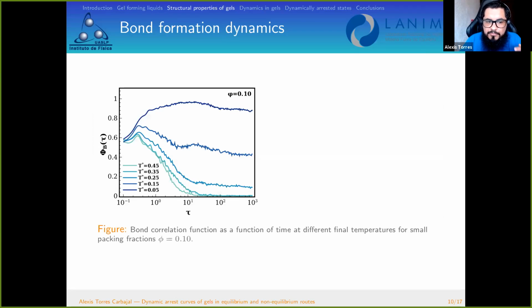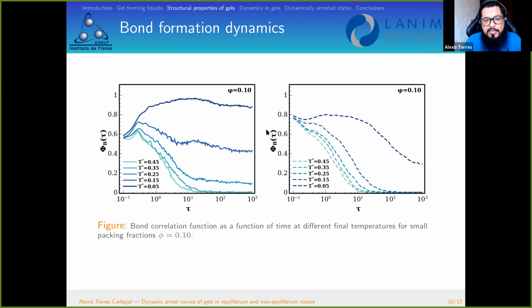So we determine this correlation, and we found that, for instance, at low packing fractions, the Lennard-Jones fluid at low temperature exhibits an increasing formation of bonds, and the time that these bonds live is longer than in the case of the Lennard-Jones with Yukawa tail. So the first message here is that the bond lifetime in the Lennard-Jones with Yukawa repulsion is less than in the Lennard-Jones, and also the number of bonds in both fluids is different. This is related with the kind of structure that we see at the final states, which we call the asymptotic time.